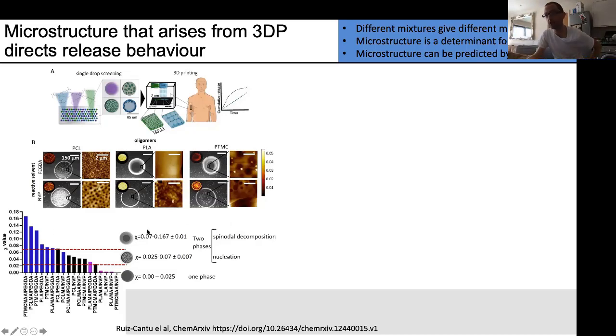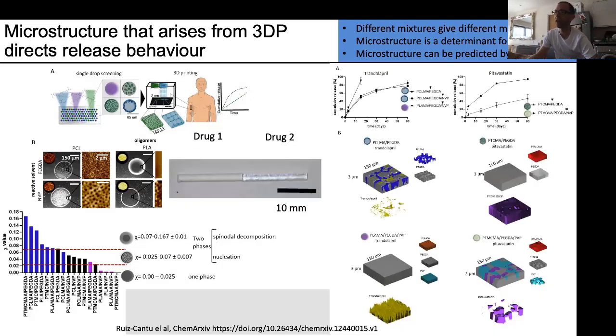And we found that we could classify all our microstructures according to the Flory-Huggins interaction parameter, ranging from homogeneous to dispersed material to complete separation in a core shell type of environment. And then when we printed it and looked at the microstructure with ToF-SIMS and aligned that to the kind of behaviors that we're getting when we did dissolution, we found that we saw the same kinds of microstructures in 3D printed structures that we saw in a single drop, and we're able to relate essentially this screen as a predictive element or a predictive guide to what we should expect from a 3D printed, or at least an inkjet printed structure.